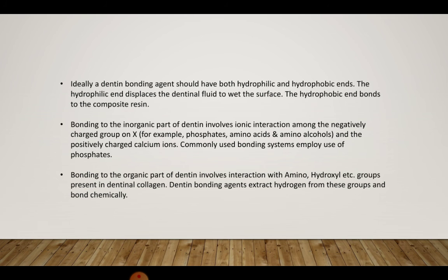Ideally, a dentine bonding agent should have both hydrophilic and hydrophobic ends, as I already explained. The hydrophilic end will displace the dentinal fluid to wet the surface, whereas the hydrophobic end will bond to the composite resin. Now, bonding to the inorganic part of the dentine involves ionic interaction among negatively charged groups on X, for example, phosphate, amino acid, amino alcohol, and the positively charged calcium ions in the hydroxyapatite crystals. Commonly used bonding systems employ phosphates.